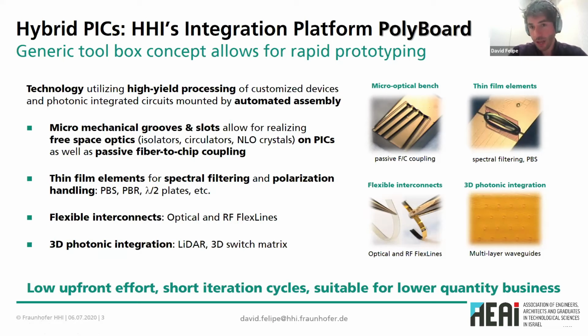And as a last very interesting aspect of the polymer integration, there is the so-called 3D photonic integration. Here on this picture, you can see a cross section of a polymer waveguide chip, in which each one of these small squares is a waveguide, and we can stack them up to achieve 3D photonic integration. This is interesting, for example, if you want to attach multi-core fibers to the chip, or if you want to overcome unending crossings in very complex waveguiding networks. You can route different waveguides to different layers and then be able to route without increasing the number of interconnects. So this is a short perspective of what these polymer waveguides can do.